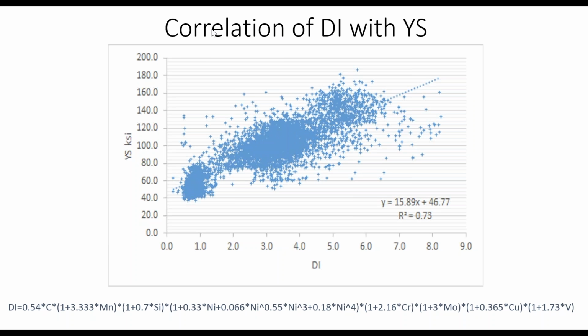So if I take my data set of all the data, DI is the ideal critical diameter. It's a heat treatment idea of how thick the section can be and be heat treated into the center. It's based on chemistry. And so here is the chemistry calculation traditionally for the ideal critical diameter. And you can see that I get about a 70% correlation. And this is from chemistry alone without tempering temperature or anything else. So it's really pretty loosey-goosey, but I still get a nice tight correlation. Clearly you can see the 3 data sets. This is the carbon steel, this is the 8620, and this is the 4340.